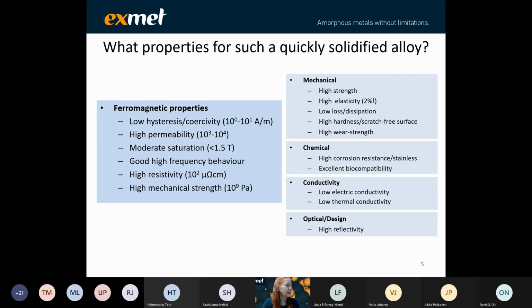In this webinar, I believe the ferromagnetic properties are the most interesting ones, so therefore they are highlighted on this page. If we have a ferromagnetic amorphous alloy, compared to the crystalline equivalent, we get a lower hysteresis, lower coercivity. We have a high permeability, moderate saturation, a good high frequency behavior, high resistivity, and also the high mechanical strength.